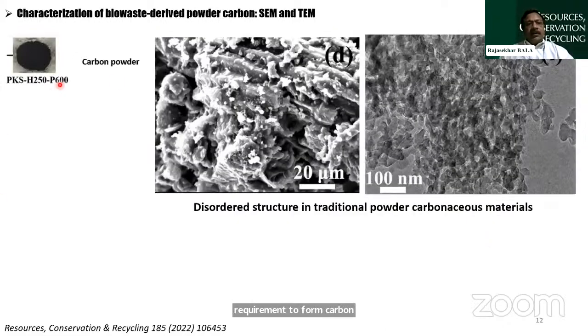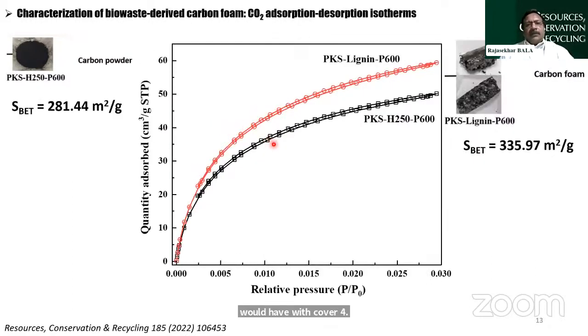The presence of sp2 hybridized carbon is an important requirement to form carbon foam, which we managed to achieve through our synthesis. On the other hand, if you look at the carbon powder that you produce conventionally using the same hydrothermal reactor with no pre-treatment, you have heterogeneous carbon particles that are not aggregated. They don't form a macromolecular structure, and therefore their properties are relatively inferior to carbon foam. Then we compare the adsorption capacity in terms of removal of carbon dioxide, the so-called greenhouse gas that contributes to global warming and therefore climate change. These two materials are both able to remove carbon dioxide. However, the lignin-based carbon foam is able to remove more carbon dioxide than the carbon powder. That's a key outcome of this result.